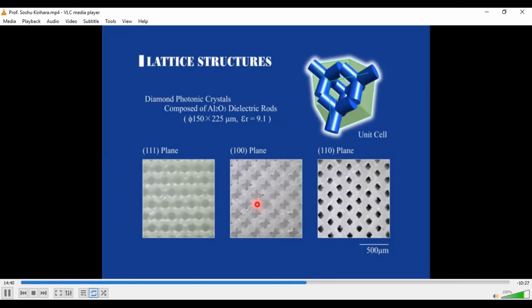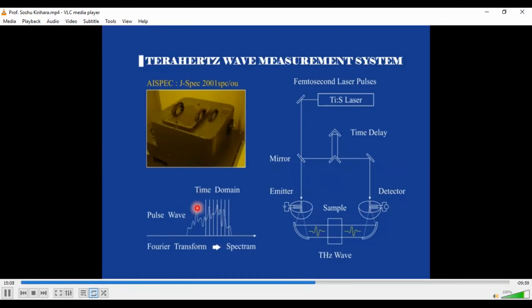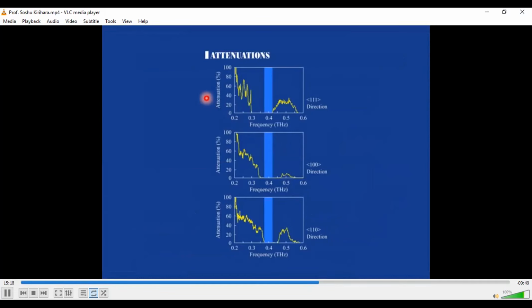treatment processes. The terahertz wave property was measured by using an optical system like this. At first, a femtosecond laser beam is incident on micrometer-order antennas and generates the terahertz wave, which transmits through the sample and is detected by the same shape of micro antennas. We can obtain the intensity and time pulse data, and by using Fourier transformation, we can obtain the transmission spectrum.